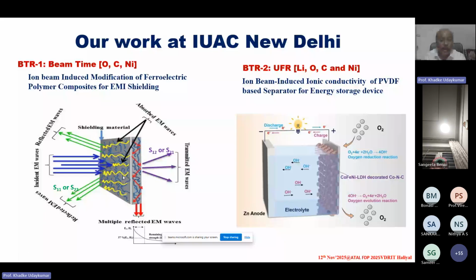And we have used different types of ions, which increase the dielectric constant or increase the conductivity of the material. To increase the conductivity of the material, we took a carbon beam. We saw that the conductivity has been increased. And in order to increase the dielectric constant, we used an oxygen beam. So the appropriate type of beam, appropriate energy, and appropriate fluence have been used in order to modify the polymer material for EMI shielding and as a separator in a battery. So these are the two important results I just thought of explaining.